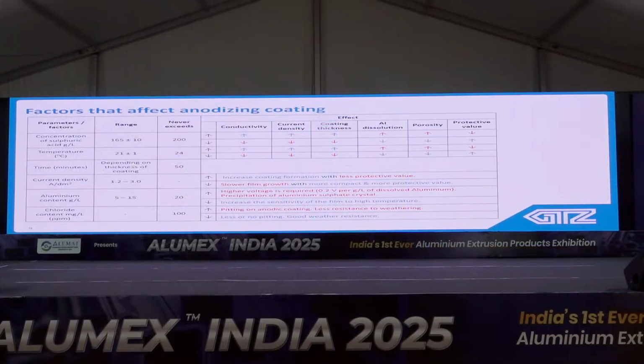These are the factors affecting the anodic coating. There is the electrolyte, that is sulfuric acid. The optimum range is 160 plus or minus 10. The maximum is 200, but you can increase the concentration beyond 200 by using some additive for anodizing. For hard anodizing, the temperature required is 21 plus or minus 1 degree, maximum 24. If you increase the temperature, the conductivity will increase, the current density will also increase, and the coating thickness will also increase. But the major drawback is that the protective value will decrease. That's why this is the optimum temperature.